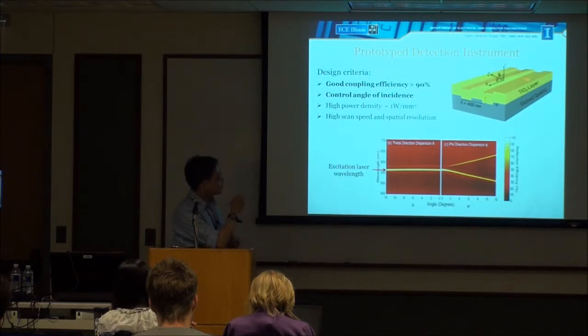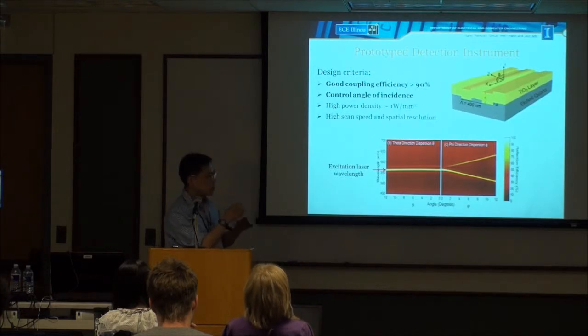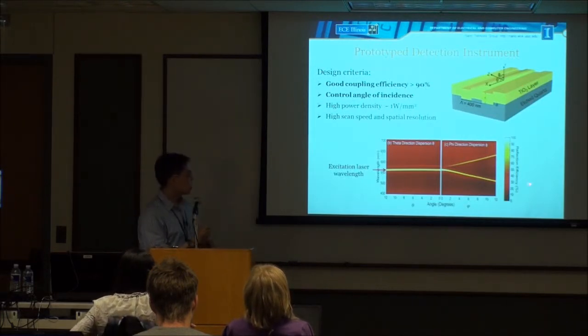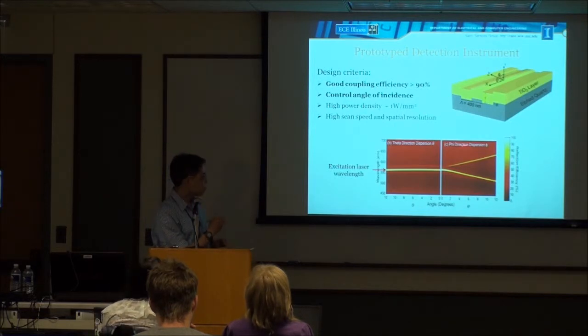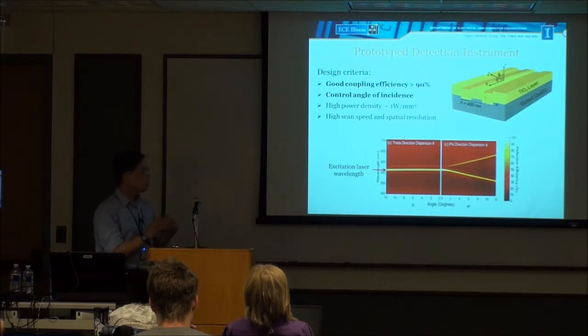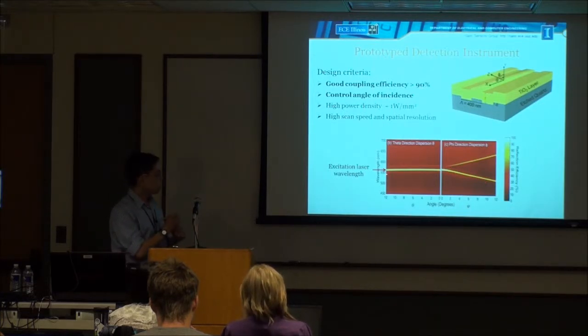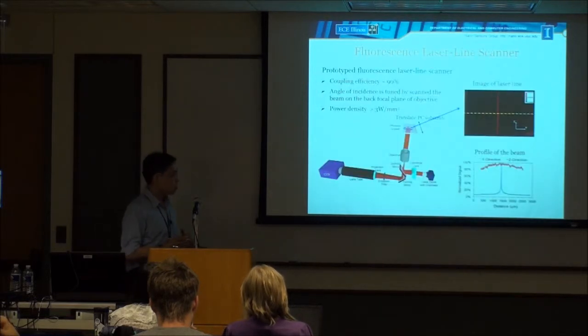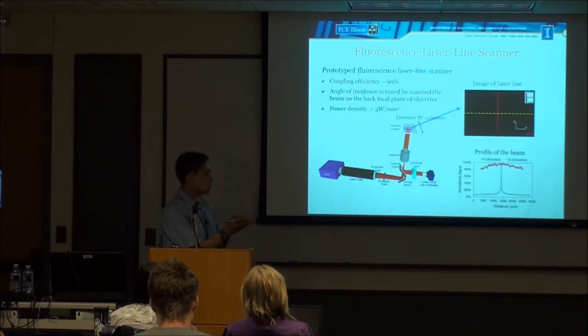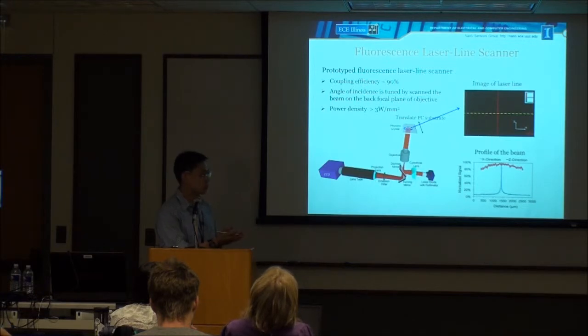However, if you illuminate along the phi direction, which is perpendicular to the grating period, it will look different when you change the angle. The band diagram is very sensitive to angle change. So this tells us we want an illumination that doesn't have any angle variation along the phi direction, but can have angle variation along the theta direction. That illumination will look like a line. So we can focus the laser into a line, and we can still couple the incident laser with the resonance mode of the photonic crystal pretty well.